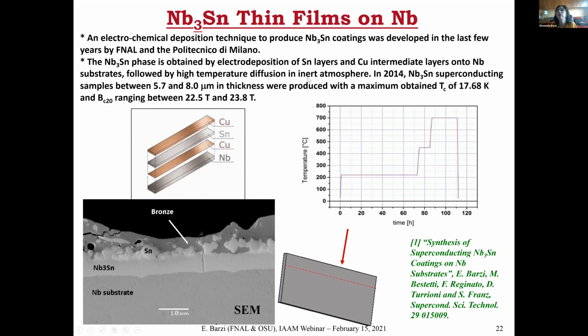In order to produce niobium-tin films, we tried all sorts of methods, from sputtering to atomic layer deposition, etc. And finally, we found out that simple electrochemical deposition works very well. So in collaboration with the Politecnico di Milano, we were able to develop a recipe. You can see we took a niobium substrate and did electrochemical deposition of a copper layer, a tin layer, and a copper layer, because to diffuse the tin in the niobium, if you have a three-element system, adding the copper, you can obtain the diffusion at much lower temperature than if you had a binary system. That's why we put the copper in there. Anyway, so we were able to produce this niobium-tin layer here.